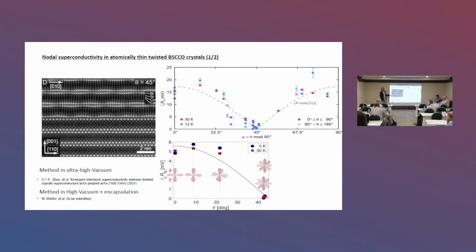Also, the TEM image of a 45-degree junction tells a lot. Of course, TEM cannot tell all. For example, I cannot see light oxygen elements. So when you see a TEM image, it's very nice, but where is the oxygen, right? My sample could be insulating, okay? So this is the problem of this material. But anyway, this is nice and unprecedented quality. You can see the D-wave, the superlattice incommensurate structure modulation that is appearing exactly at the interface where I have exfoliated and restacked the sample. So these are the bismuth, the strontium, the copper, the calcium atoms, and oxygen.